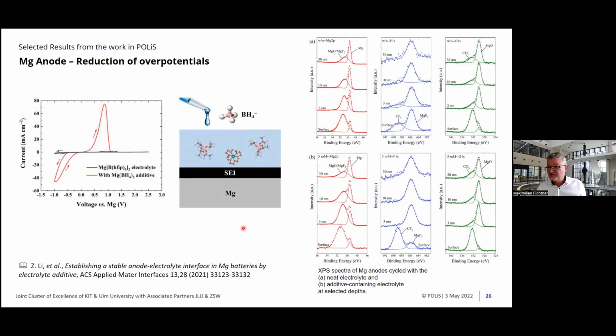That this is not only possible by this bismuth, but also by other compounds is shown here. What was done here is that another additive, magnesium borohydride, was added in a tiny amount, and this forms a particular SEI layer here, which enables the magnesium to work from the very first cycle on. We haven't quite fully understood what happens here. It's obvious that the borohydride has a strong reductive capability, and maybe the surface gets reduced. We do not get really clear evidence from XPS, so this certainly needs further studies in order to better understand that. But I would say the phenomenological effect is quite clear and convincing.